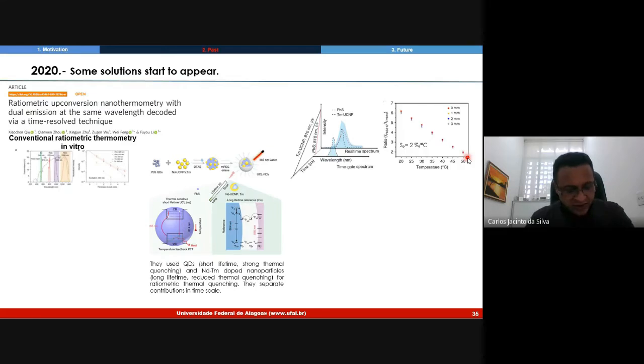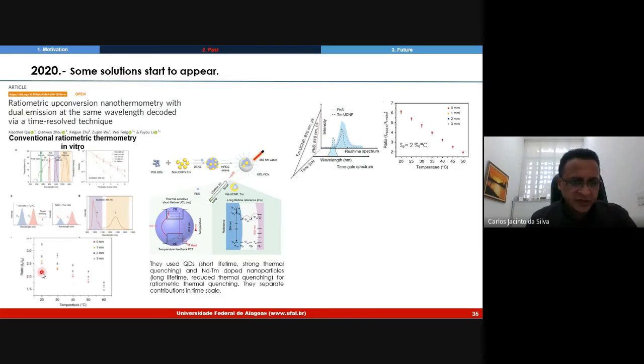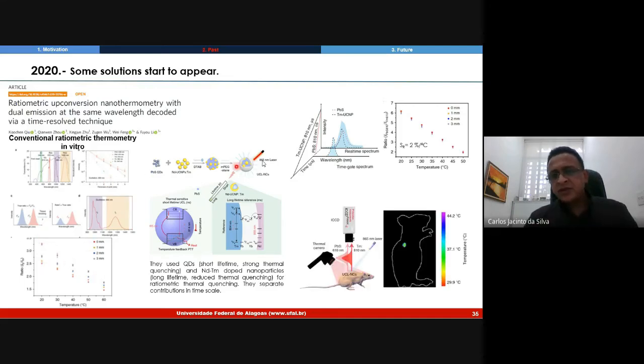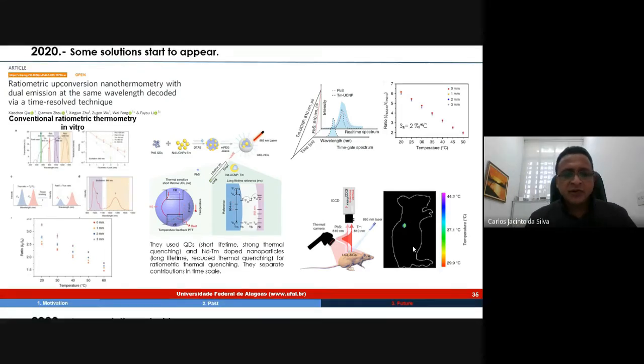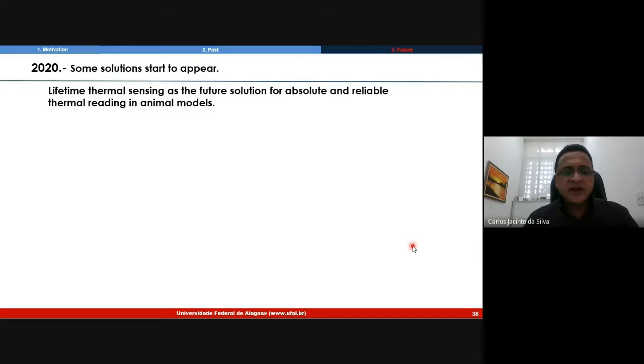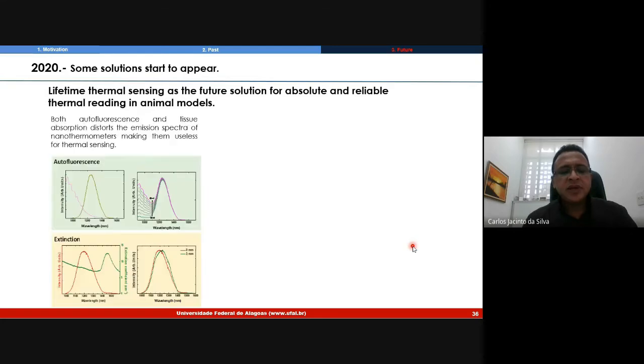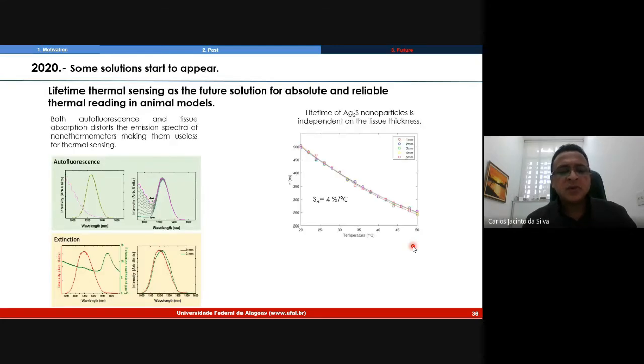This demonstration is very important, and is opposite to conventional ratiometric thermometry using two bands emitting at different wavelengths. Of course, we have here a strong dependence on the thickness of the tissue. And using this system, it demonstrated very interesting results in vivo. A thermal sensor based on lifetime was also demonstrated as a possible solution. This is an absolutely reliable thermal reading in an animal model.